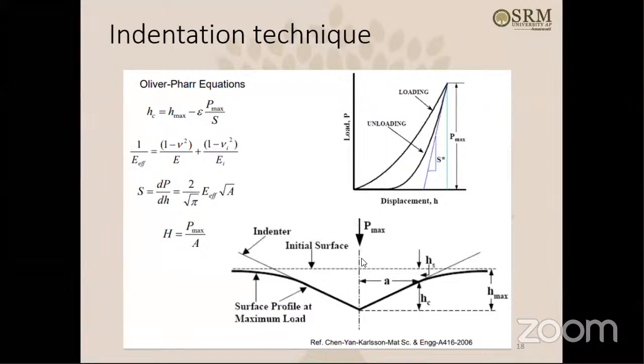Okay, you load the indenter and it goes up to some depth and then comes back, unloading. If you perform this test, loading and unloading, this is how we get this plot: load versus displacement. As you can see, there's a loading curve. It reaches the top, and when unloading starts, of course, it is not going to follow the same path here because the metal is getting indented and displaced.